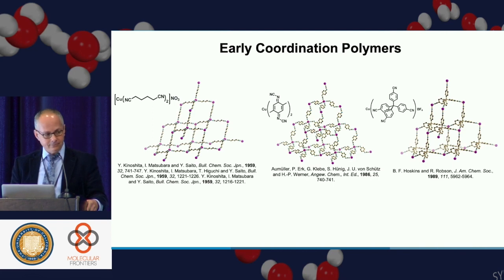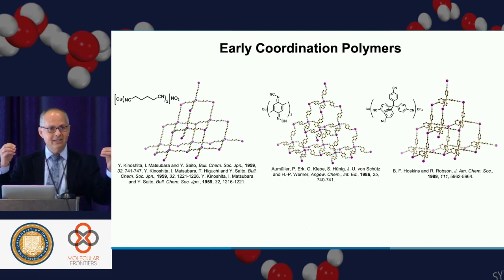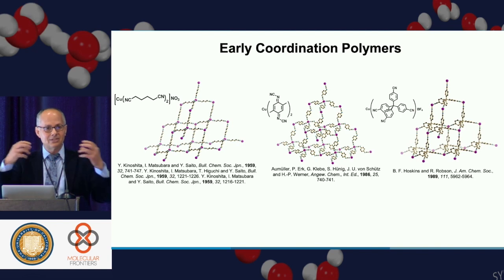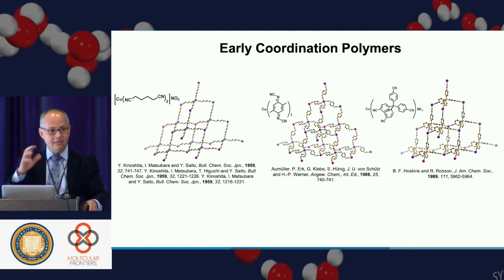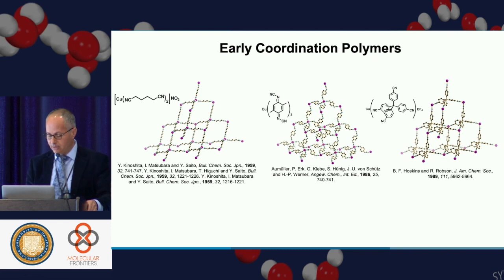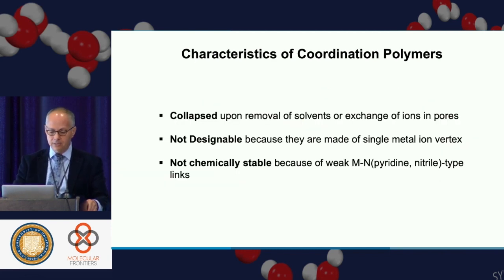And the problem is that we started working with these. It was very attractive. I mean, you have an organic linker, a metal ion, can stitch these things together, and potentially, if I can use this porosity, it would be amazing. I can fashion the pores. I could do many things that organic chemists can do with linkers and inorganic chemists do with metals. But it turns out they were completely useless. They were just nice sculptures, but they didn't do anything.